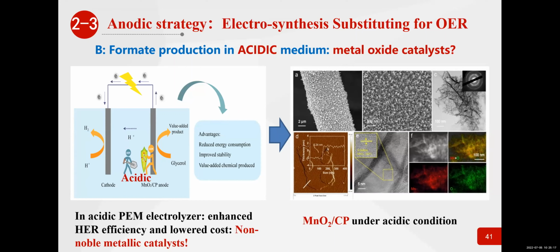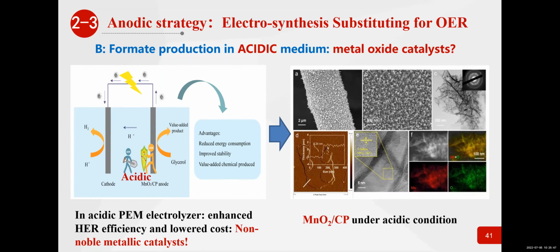non-noble metal oxide catalysis is not applicable in the acidic media. For example, manganese oxide can be dissolved in acidic media. However, we found that by adding some kinds of organic molecules, for example, glycerol, this kind of metal oxide catalyst can be stabilized, not be dissolved in the acidic electrolytes.